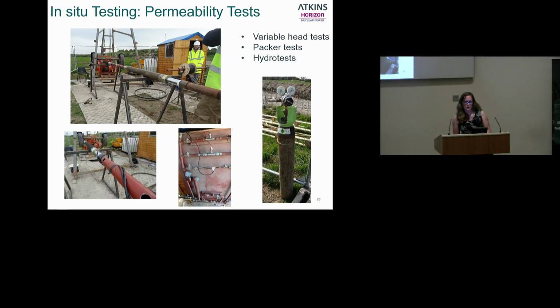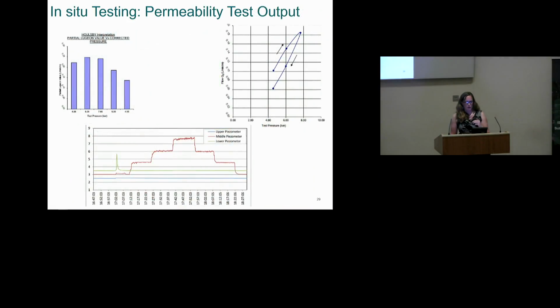Permeability testing, we did variable head tests in the superficial deposits, and then packer tests and hydro tests in the bedrock. Quite a lot of these, maybe 5-meter spacing down particular boreholes. It was a stipulation that there were going to be electrical transducers put below the test zone, in the center of the test zone, and above the test zone, so we could check if there was any 3D flow and that the packers were actually holding the test zone pressure as required.